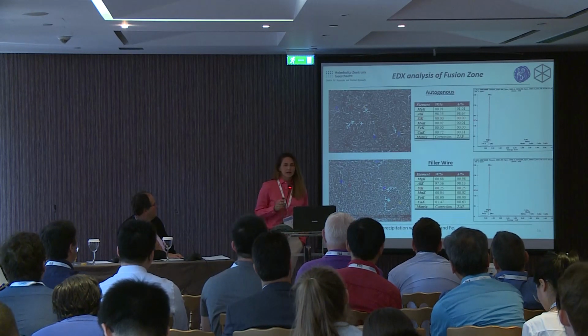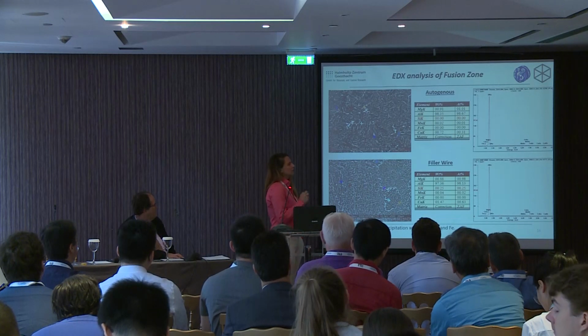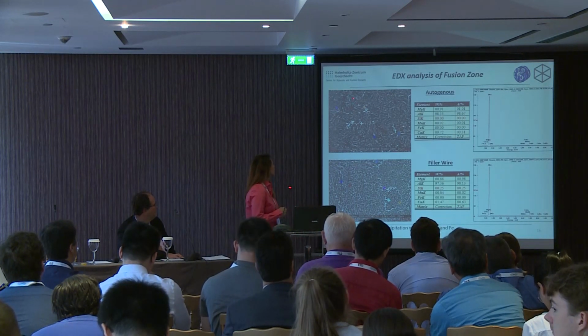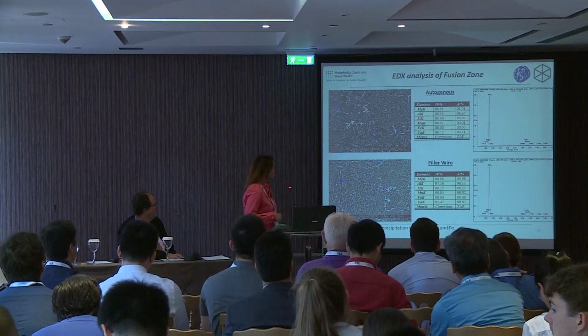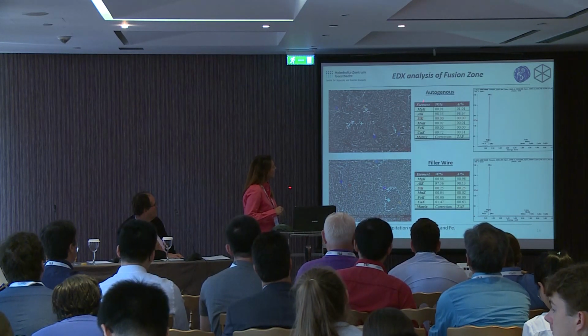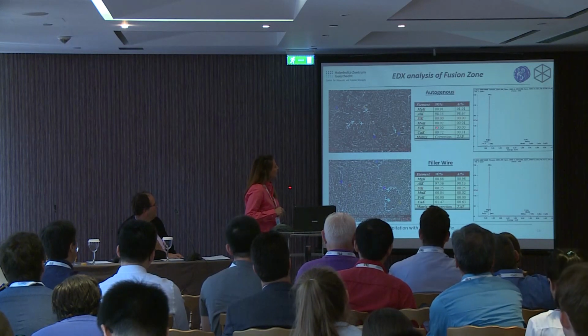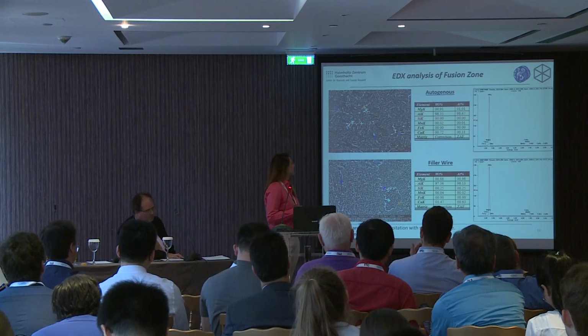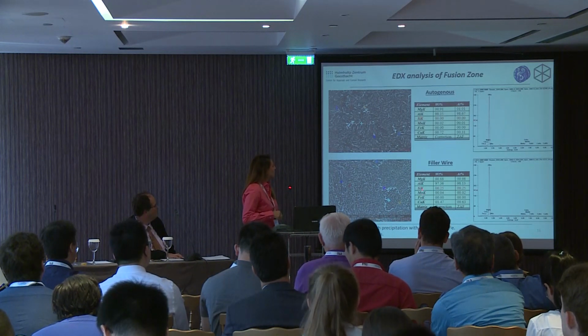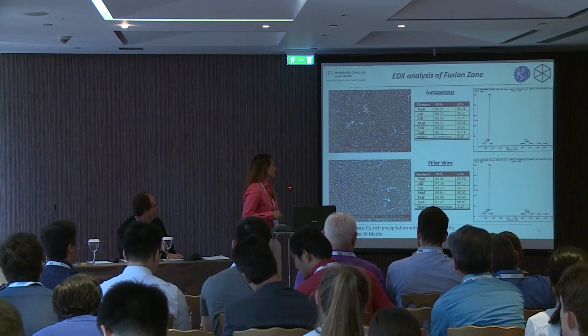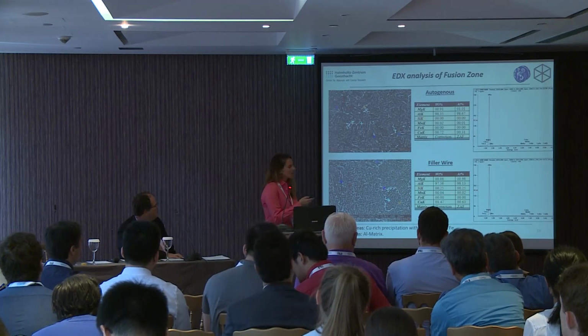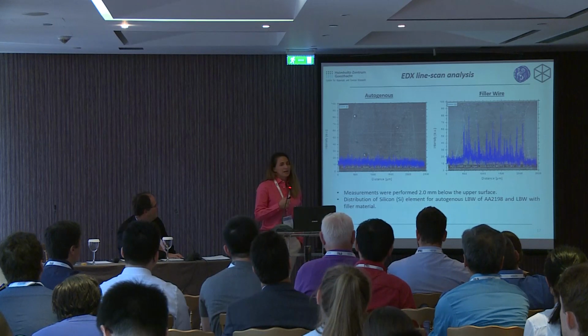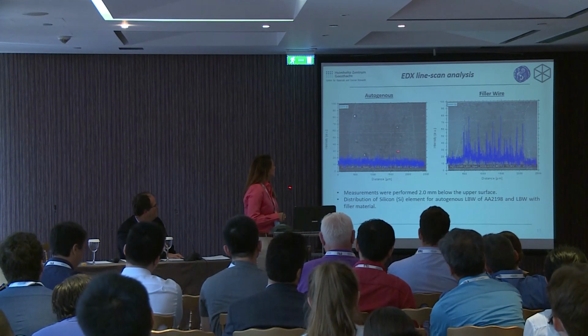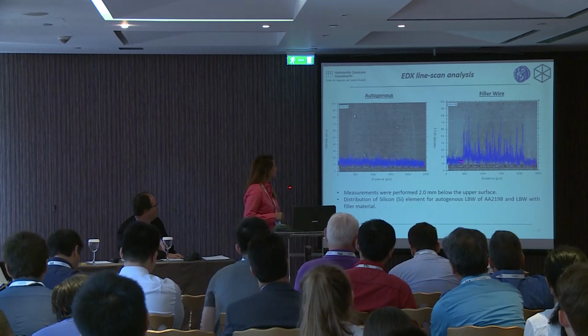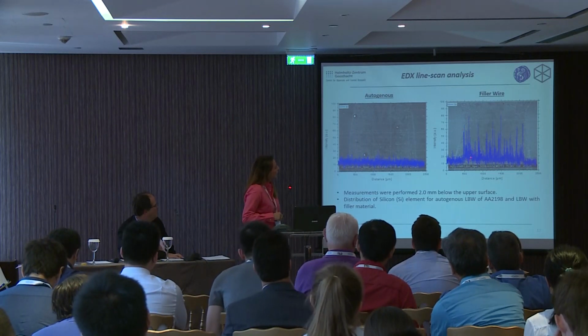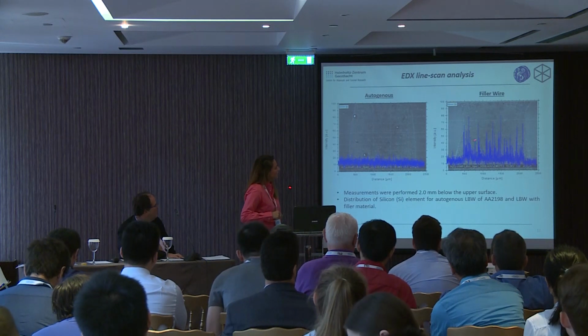We did also EDX analysis for the fusion zone. We collected 6 points, 3 in the bright areas and 3 in the dark areas, for autogenous and for filler wire. Here we have the amount of silicon, which of course in the fusion zone of the material with filler wire is higher. Also, we did EDX line scan analysis. You can see for autogenous and filler wire that the distribution of silicon, of course, is different. We have higher distribution of silicon in the fusion zone.